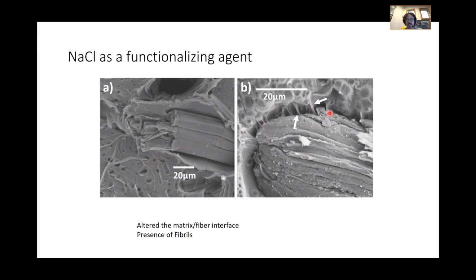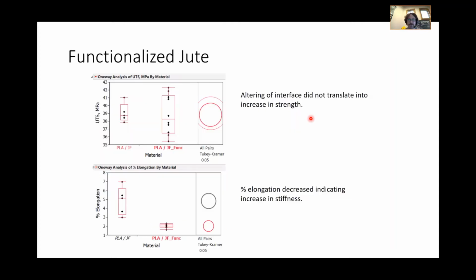When we did functionalize it - this is functionalized - we noticed this, and this is called fibrils. The fiber still pulled out, but the plastic didn't want to give it up. The plastic held on more to the fiber and formed these fibrils between the fiber and the matrix. So we actually improved the matrix fiber interface.